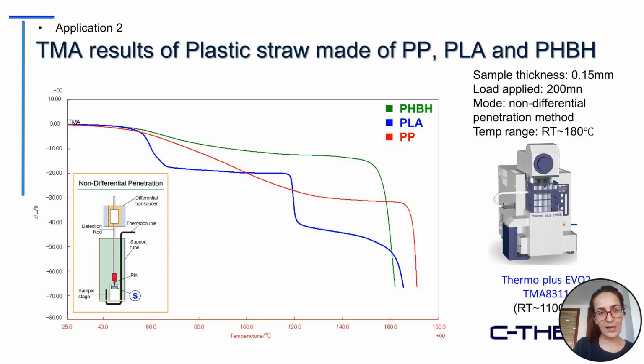Since the thermal analysis of these samples was really interesting for us, the last experiment that we did was the thermomechanical analysis of the plastic straw made of PP, PLA, and PHBH. The sample thickness was 0.15 millimeter, the load applied was 200 millinewton, and the mode was non-differential. The sample was heated from room temperature to 180 degrees Celsius.